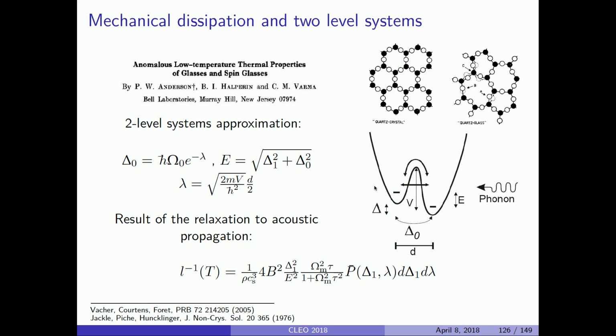This leads to very universal phenomena, a so-called tunnel plateau for these materials, and leads to acoustic attenuation that is within an order of magnitude for nearly all amorphous materials. No matter what it is, if it's wood, glass, or some other material, as long as it's amorphous, you cool it down to about 10 Kelvin, it will all follow this typical tunnel plateau. And then the only unknowns are the density of these two-level systems, their vacuum coupling rate, and their tunnel splitting.